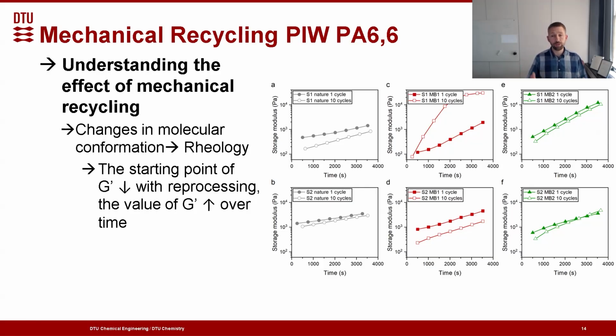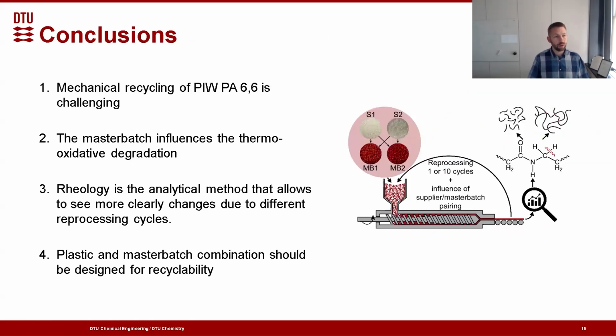So this very clearly shows that there are differences between the different systems, which relates to the supplier and the master batch combinations. We have also done tests, which I don't have the time to show, to look at antioxidant properties to see if we can suppress that. That is not possible. So this is directly a result of the formation of these different functional groups that I showed you in the first place.